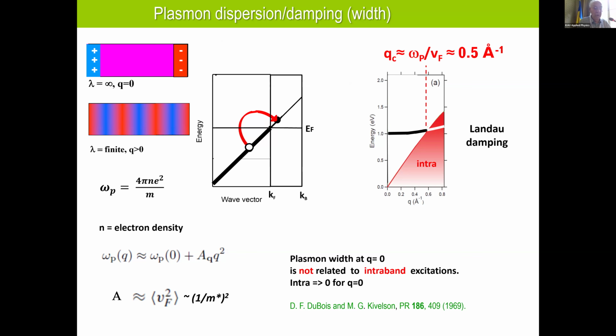It starts, for example, at 1 eV, and then you can do excitations at shorter wavelengths, higher momentum, and then you have to compress the electron liquid, and this needs energy, and therefore you see a dispersion of the plasmon to higher energies. But then when this plasmon dispersion merges into the Lindhard continuum of single particle excitations, it decays into single particle excitations. Now the plasmon energy is determined in some way by the electronic density, and the dispersion coefficient is determined by the Fermi velocity squared, averaged over the Brillouin zone.